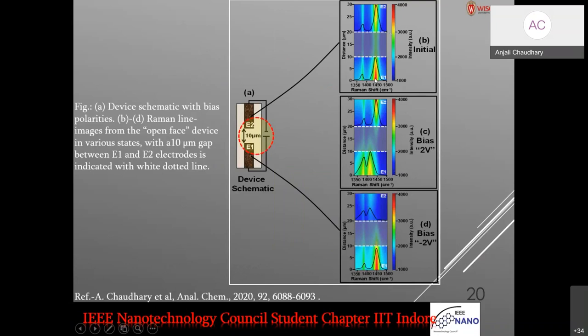Initially, there is no shift in the peak position in Raman. As you see at 1380 and 1450, the peaks at the E1 and E2 electrodes remain intact. But when you apply a 2 volt bias to the E1 electrode, you see that these peaks come close together, because due to the polarons, you are modifying the structure of the polymer and affecting its vibration. That's why they get shifted in the Raman, which is a signature for getting the vibrational peaks of the molecule. And when you apply minus 2 volt, which effectively means E2 is positively biased, the same phenomenon is traced on the E2 electrode. So this is how, by polaron formation, the electrochromism took place in the P3HT based device.